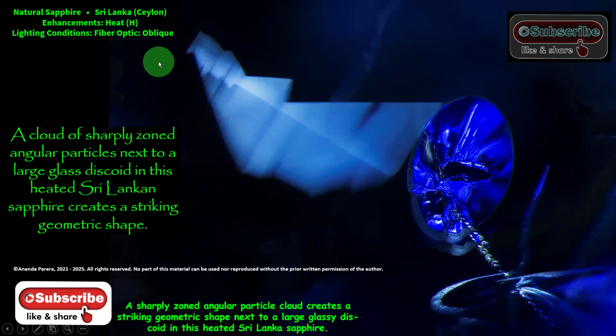the lighting condition here is fiber optic oblique. The stone is a Sri Lankan stone. It is a heated stone. A cloud of sharply zoned angular particles next to a large glassy discoid in this heated Sri Lankan sapphire creates a striking geometric shape.